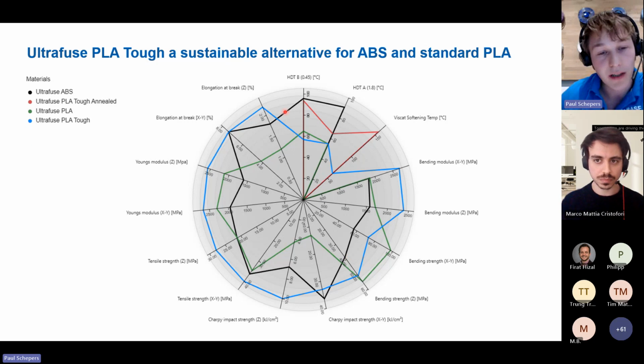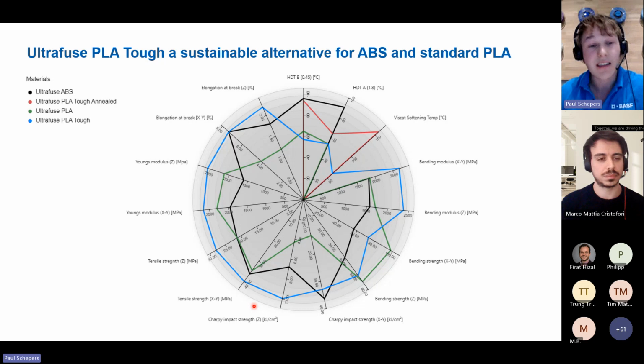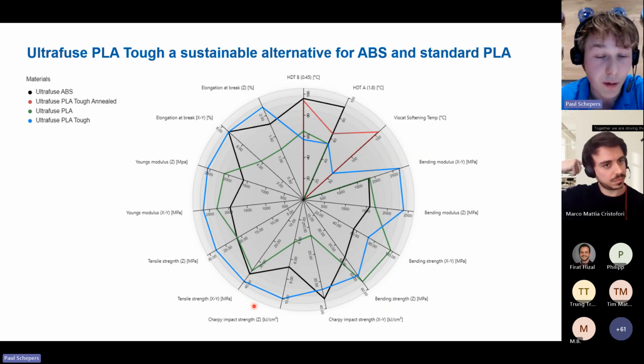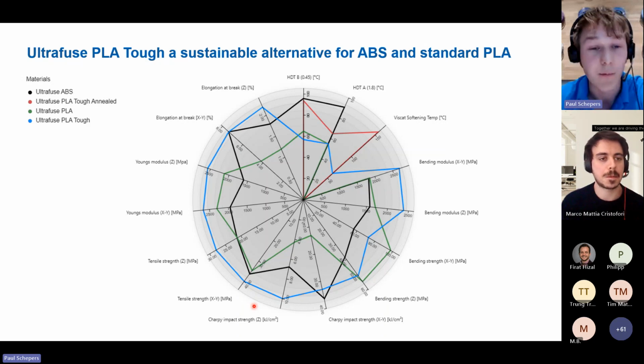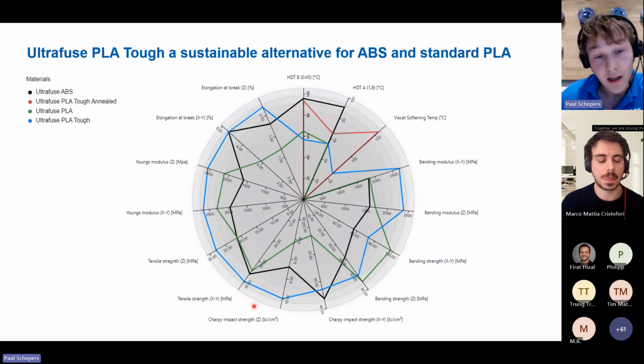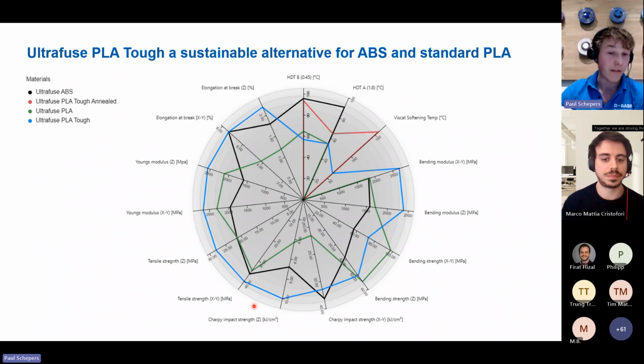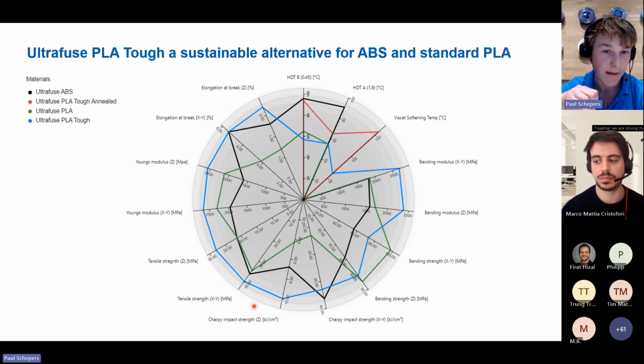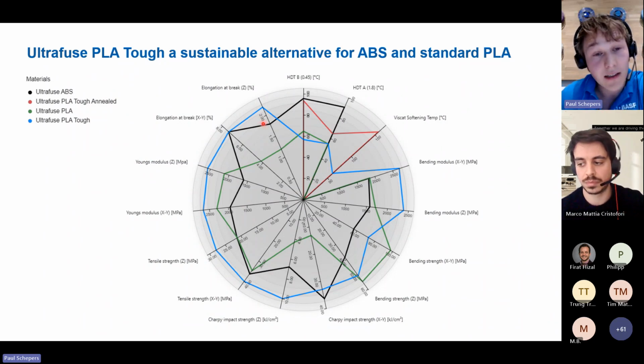And in blue, we have PLA Tough. So we know that PLA and ABS both have limitations. PLA is quite brittle, and ABS isn't the most suitable material if you think about the environment or if you want to print without styrene emissions. But it also shows, for example, one of the most crucial factors in FDM printing: if you want to have very strong parts, you don't want delamination, and delamination occurs quite often in the Z orientation. What you see on the top is that both PLA, in the green, and ABS, in the black, are outperformed by PLA Tough. That's quite unique because that is in general the weakest link of your print.